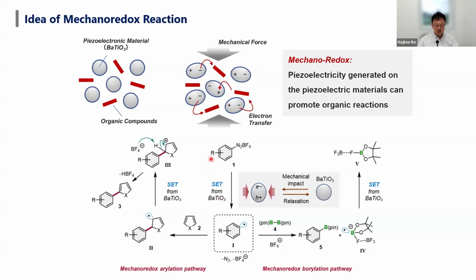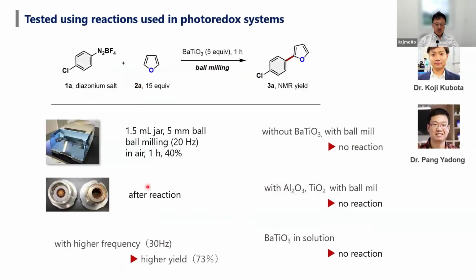We also employed some reactions that were already reported as photoredox reactions. I asked them to test these reactions using a diazonium salt and furan in the presence of barium titanate in the ball mill, and in the first shot they found very promising results. At higher frequency, they found higher yields of the reaction products.